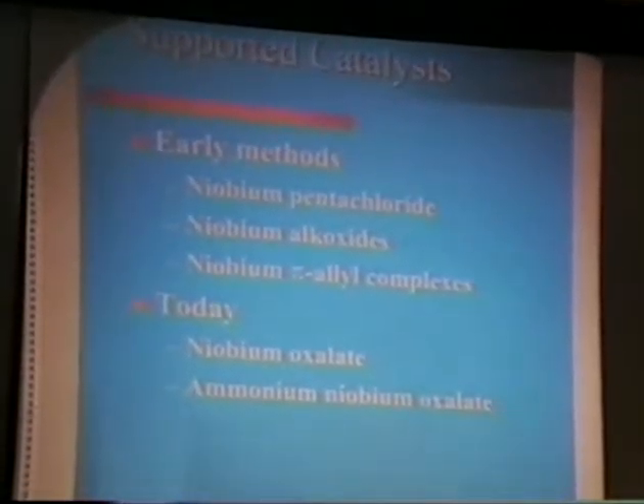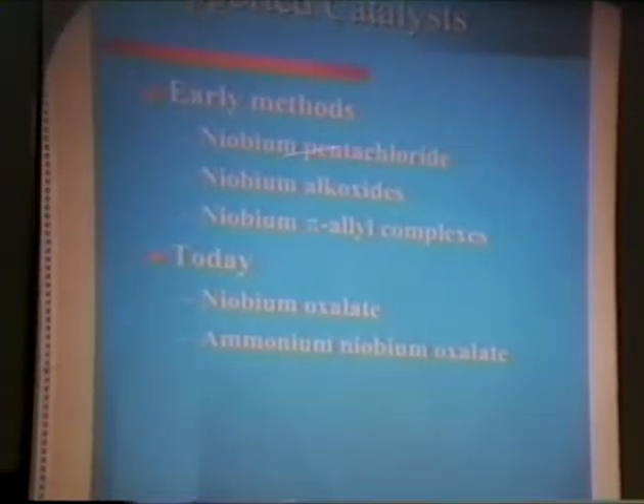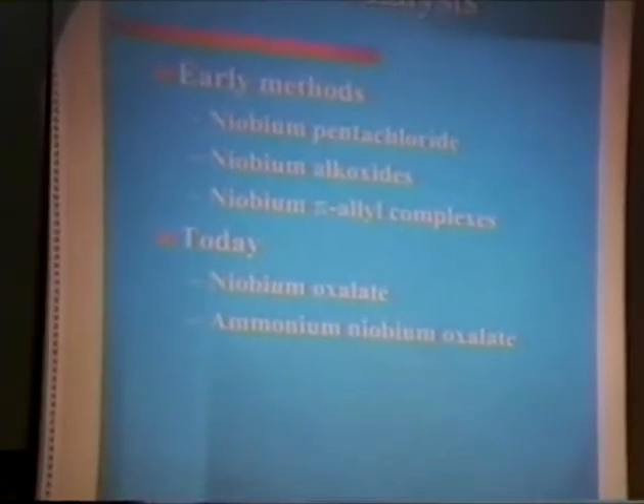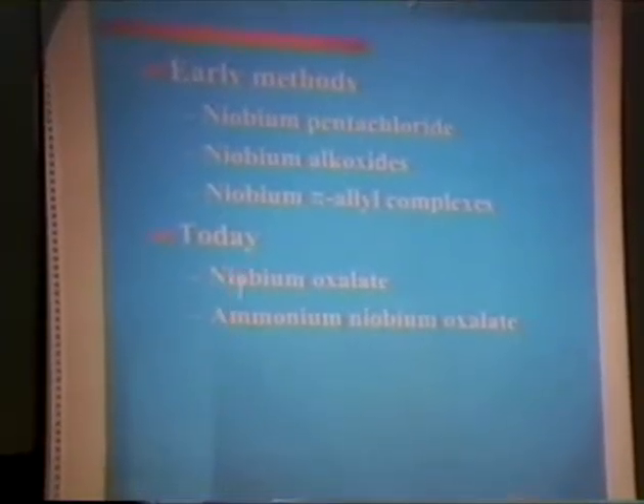Let's move on to supported catalysts. When you look at the early literature, you wonder why people even bothered, because these were the three kinds of materials that were being used to prepare them. These are all water sensitive. They're not easy to work with. But that's where the early work was done. As I mentioned, the ammonium niobates are not soluble. There is a potassium niobate that has some high solubility. Nobody wants to use it because of all the potassium. So what's evolved from this are these oxalate complexes, initially the niobium oxalate, and then subsequently the ammonium salt.